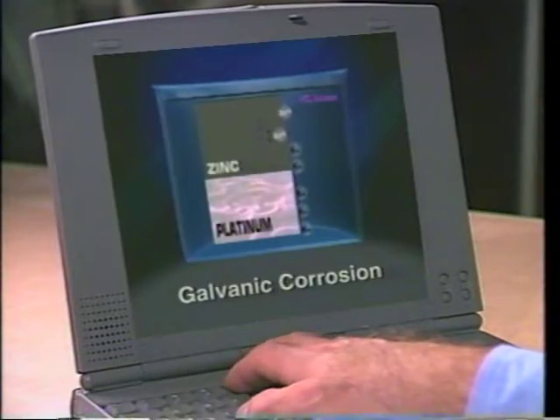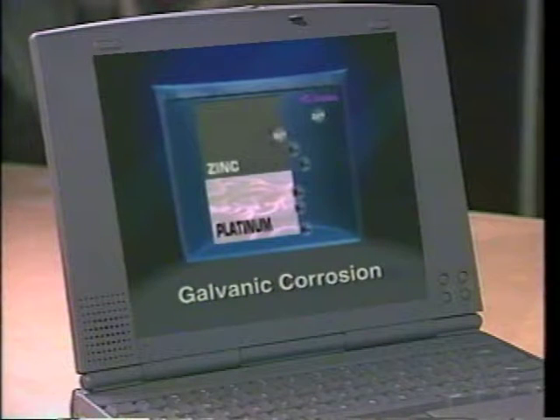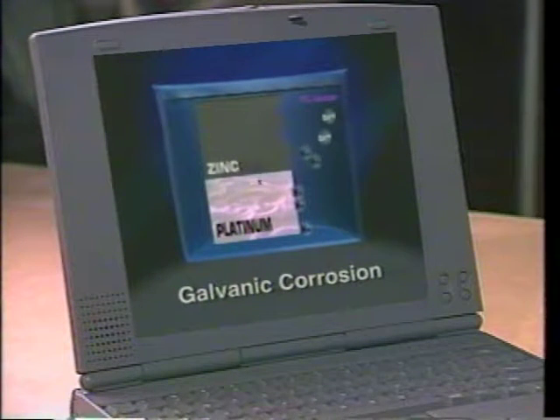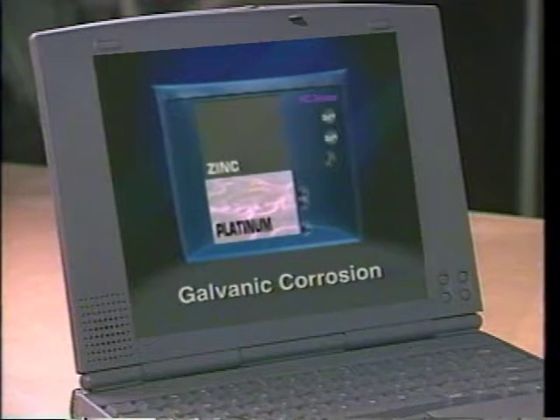Localized corrosion, on the other hand, occurs only at specific points on the substrate. It's less predictable and can cause unexpected, even catastrophic failure due to localized loss of structural integrity. There are many forms of localized corrosion known to corrosion engineers. Some of the more common forms include galvanic corrosion, which occurs when two dissimilar metals are coupled in the same electrolyte, causing the anodic metal to deteriorate.